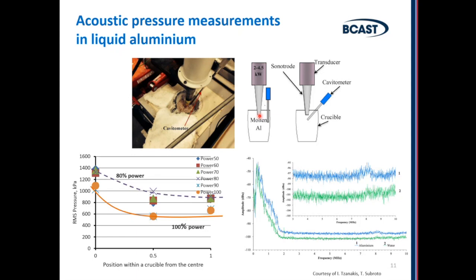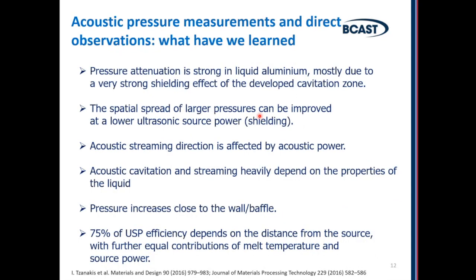And that's what we don't want. We want to treat a larger volume of melt or liquid. So we want to have enough cavitation, but not too much cavitation. And that's a very important practical conclusion from these measurements. So we learned from these acoustic pressure measurements, which I think we pioneered like 8 years ago here in Brunel, that we may have a very strong shielding effect if the cavitation zone is very well developed.